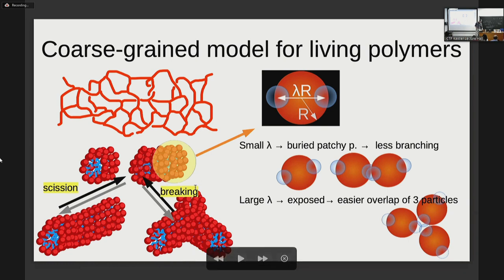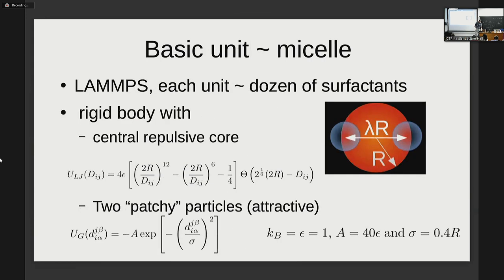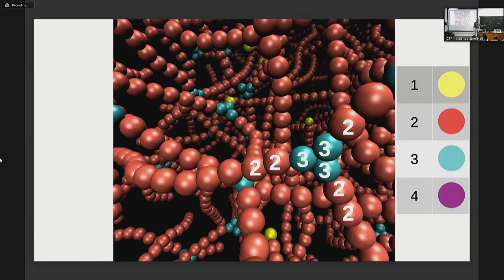So they are not really a linear polymer where the linearity is kept forever. These kind of tubes are joining and detaching all the time with what's called a scission. Or we have distinguished the breaking from scission that are different names just to talk about another process in which the cross link is broken to have a free end and a linear strand. So we had the coarse-grained model for this kind of dynamics. And we consider one of these units including a lot of these surfactants. And the blue spots are those that are sticking with each other. So this is a model for simulations in which we have this rigid unit in which you can form easily a chain of these red balls because the blue sticky points are sticking to each other. But if they are exposed enough outside of the blue, of the red hard core, there will be also the chance of having this kind of triple contacts. So the model can tune a little bit the propensity to do that by increasing this parameter lambda, which is the distance between the sticky spots.